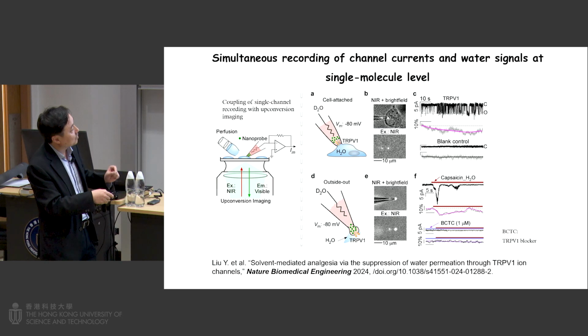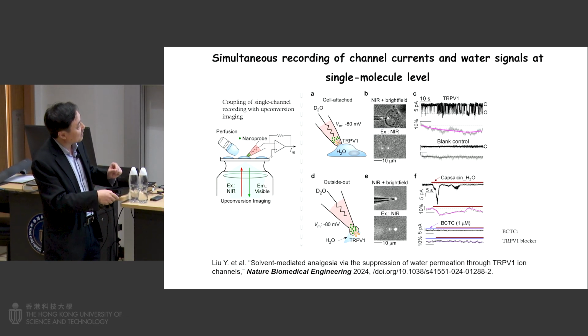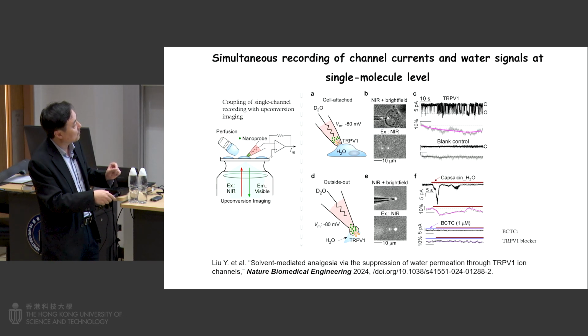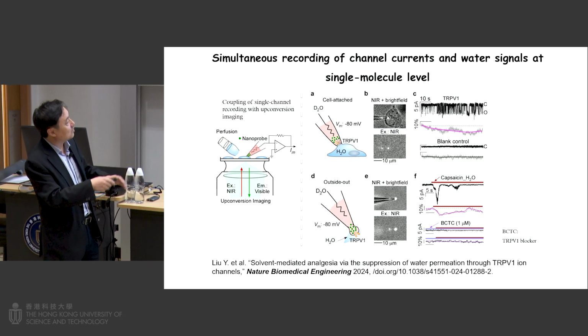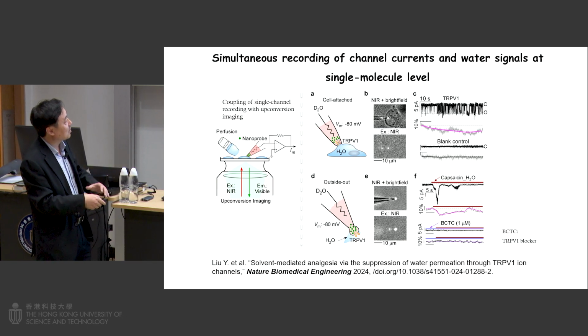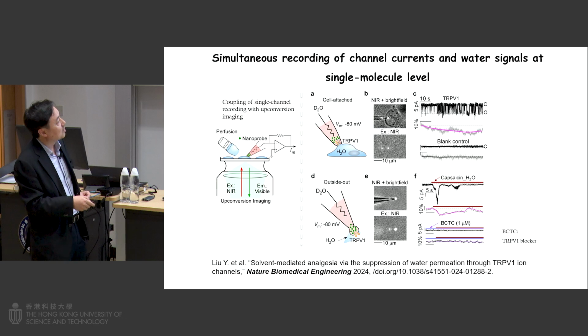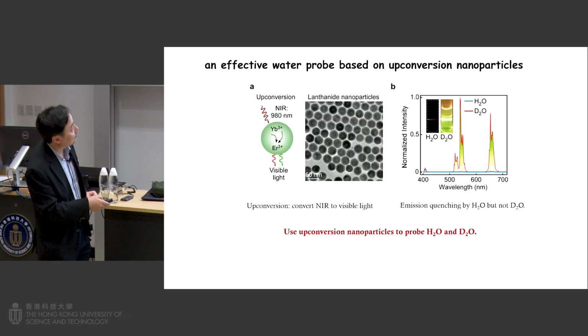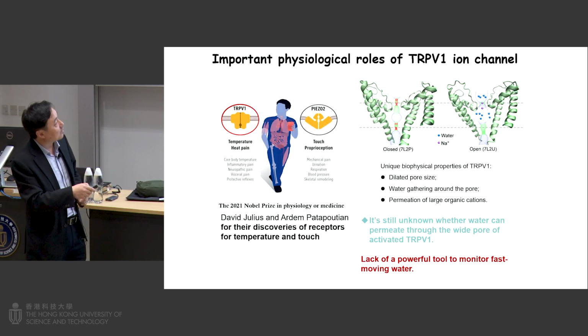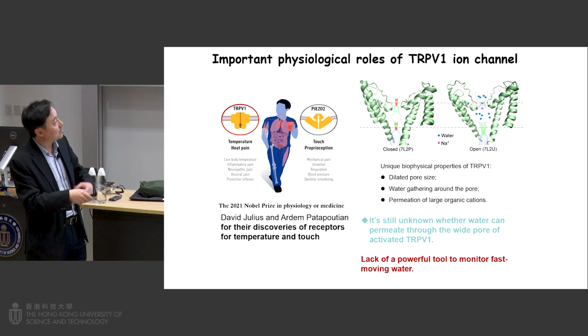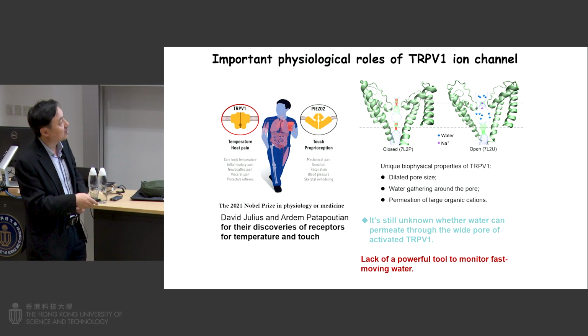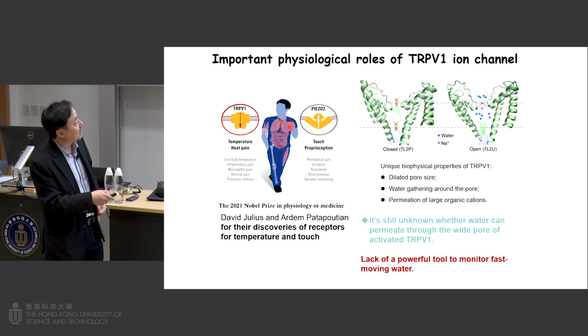So we can also do the opposite design here. You can see the D2O can go inside, and the particle is within the cell body. So we performed both experiments, and we confirm, using this setup, the conclusion is that water molecules indeed can go through the ion channel. So we use a luminescence on and off approach to confirm that.